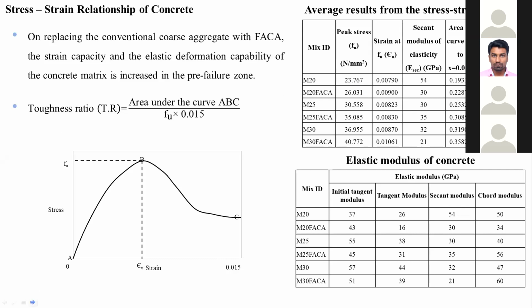In our experimental investigation, we found that the stress strain behavior is very impressive with this FACA aggregate. On replacing the conventional coarse aggregate, the strain capacity and elastic deformation capability increase, and the failure zone changes. Also the toughness ratio is increased. We know that the toughness ratio is the area under the stress strain curve divided by FU into 0.015 as per IS code.